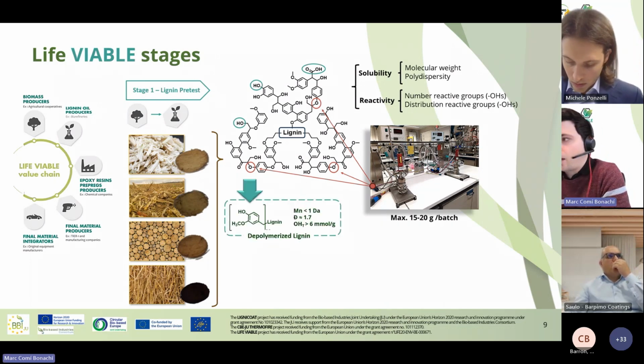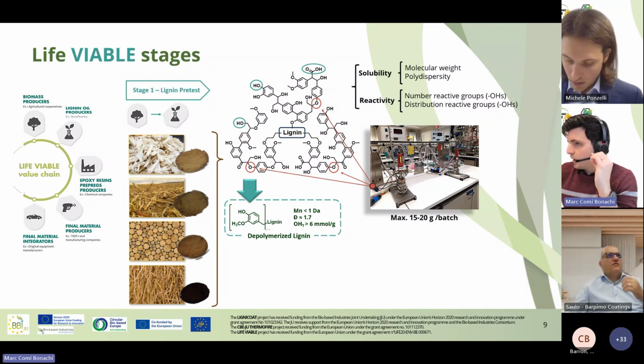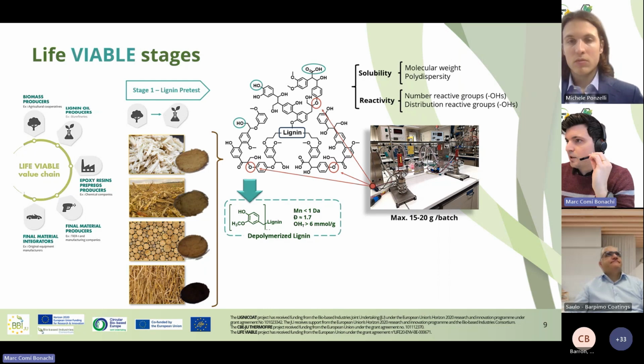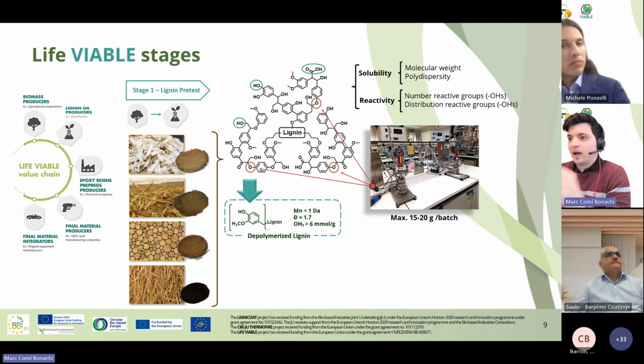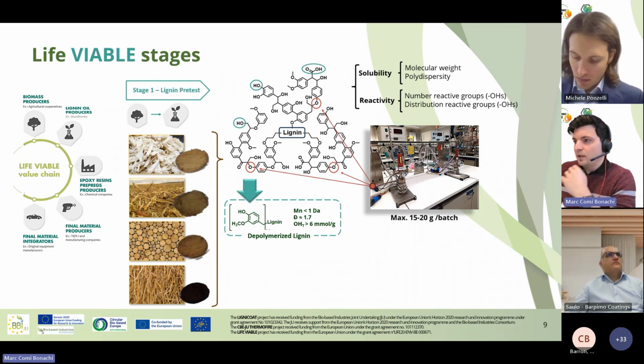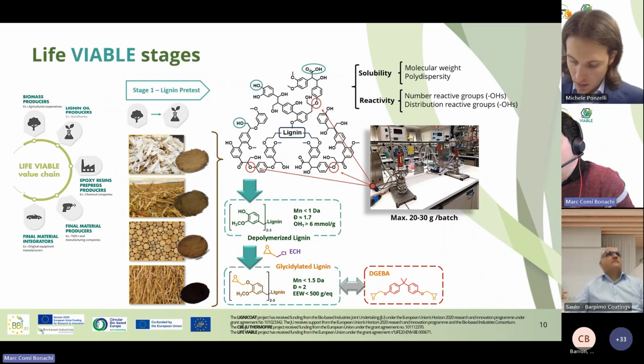When we produce the break, or the hydrogenolysis, of these ether bonds, we create new phenols and more defined, smaller molecules. So usually our target is to go from lignin raw materials that have a molecular weight above 5,000 grams per mole, or 5 kDa, to less than 1 kDa, and a dispersity going from 3 to 5 to less than 2. Also, it's very important for us to increase the OH content to more than 6 millimole per gram.